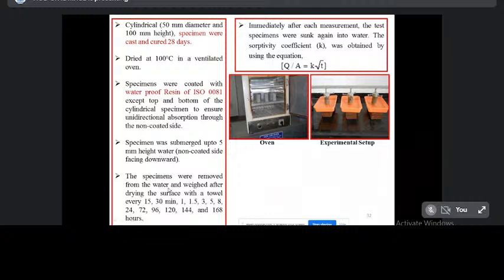Here I have used a 50 mm diameter and 100 mm height cylindrical specimen, cast and cured for 28 days. After 28 days, it is dried at 100 degree centigrade in a ventilated oven. Specimens were coated with waterproof resin except the top and bottom of the cylindrical specimen to ensure unidirectional absorption of water. Then the specimen was submerged up to 5 mm height in water. The specimens were removed from the water and weighed after drying the surface with a towel at 15-30 minutes, 1.5, 3, 5, 8, 24, 72, 96, 120, 144 and 168 hours. Immediately after each measurement, the test specimen was sunk again into the water.